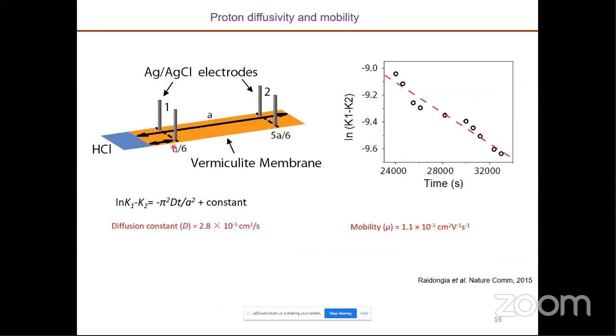Similarly, we can also measure at what speed ions are moving through the channels. For example, we can put four electrodes and measure conductivity at point 1 and point 2. On one side of the channel, we can put HCl. As HCl moves from one end to the other, the conductivity between point 1 and point 2 will change as a function of time.